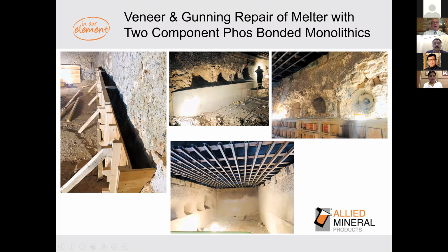As I mentioned earlier, to give the industry what they wanted on repairing old refractory, we have done 2 different types of repairs: a veneer casting, where you actually place a wooden form, and after you've cleaned this with a hydraulic hammer, then you just pour back to get to your original thickness. And you can see here in the middle picture that wall after it was veneer poured back. And then you can see again how cracked the upper sidewalls are. These are very typical pictures.